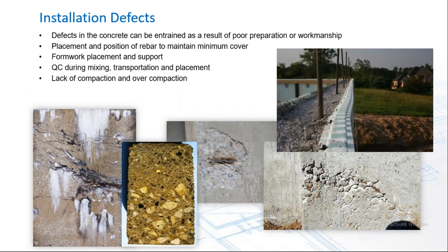Installation defects can occur frequently. The positioning of formwork is critical. Although this is an ICF form, you can see how wavy that is and doesn't give the reinforcing the entire 2 inches that's normally required in the building code, but through over compaction we can see a separation of the larger and the small aggregates, as you see there in the middle, which results in an uneven stiffness or strength